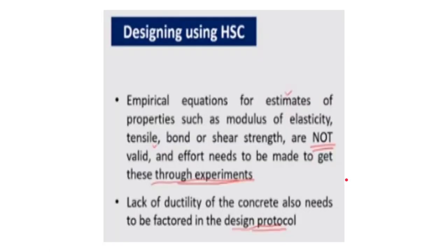Now, designing using HSC: how do we go forward with the design? Empirical equations for estimates of properties such as modulus of elasticity, tensile, bond and shear strength are not valid. These basic equations are mainly for normal strength concrete, and they are not valid for high strength concrete. Therefore, effort needs to be made to get these through experimental findings. Lack of ductility of the concrete also needs to be factored into the design protocol.